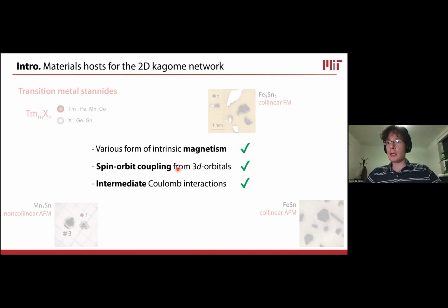And we do see the signatures of this spin-orbit coupling very clearly, both in transport and in the spectroscopy, in the photoemission measurements. And of course, because we have 3d electrons, which are more localized than the p electrons, we have intermediate Coulomb interactions. So potentially a place to look for correlated physics that's activated by the presence of dd Coulomb interactions.